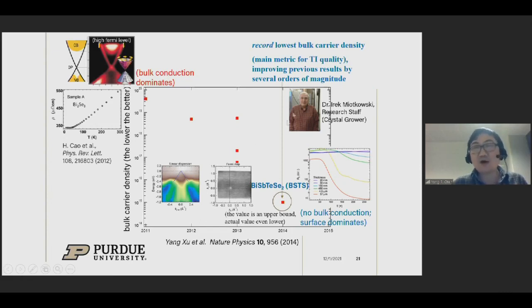So people, including us, worked hard, and particularly I credit a research staff, Dr. Miotkowski, who worked with us for several years, growing many different kinds of bulk topological insulators. Eventually we developed these very nice four-element based topological insulators, based on bismuth antimony telluride selenide, where the bulk carrier density is many orders of magnitude lower. In fact, this is an upper bound. At low temperature it is actually immeasurable. And you show a truly insulating bulk, the conduction becomes negligible at low temperature, and all the conduction is from surface electrons. So that's the key. This record lowest bulk carrier density is key to having a high quality topological insulator.